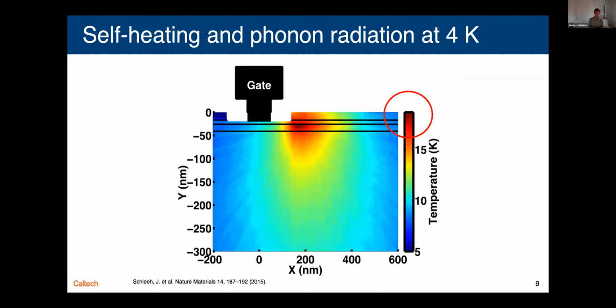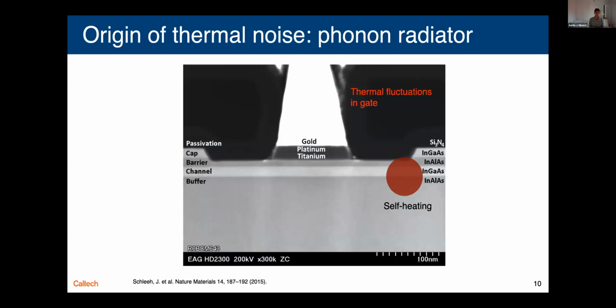So at cryogenic temperatures, as many of us know in this community, heat conduction occurs by phonon radiation rather than by diffusion. And so the phonons are being radiated out from this hotspot, and those hot phonons are impinging on the gate metal and heating the electrons, and the electrons then exhibit this thermal noise. And so that's what I'm trying to convey here: rather than diffusion at 4 Kelvin physical temperature, the self-heating can be quite substantial, on the order of 20 Kelvin. And so that means the gate metal itself is not at the same temperature as the physical temperature of the amplifier.